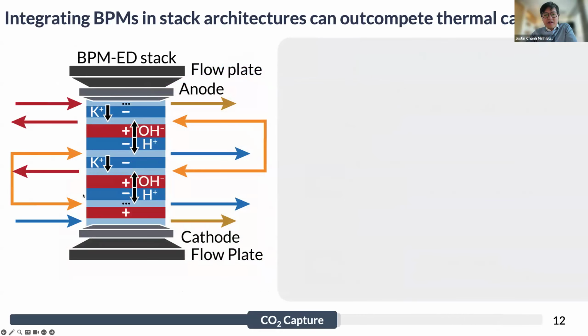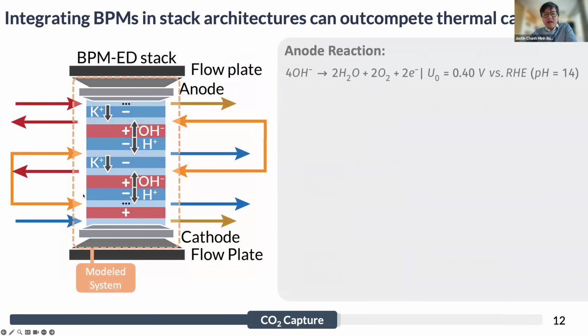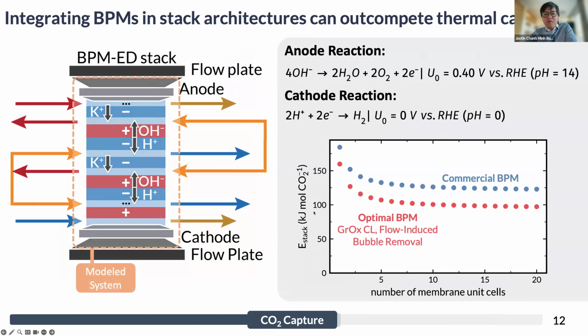The last thing we can do, understanding these things, is design an optimal system where we can put the membrane into an overall stack simulation and understand how we can improve the performance of these systems. And we see that the best way to go from the commercial bipolar membrane system that we've been working with Aowen to a more optimal one would be to improve the catalyst layer to eliminate that kinetic overpotential, as well as introduce some sort of way of shearing bubbles off the surface with flow-induced bubble removal.